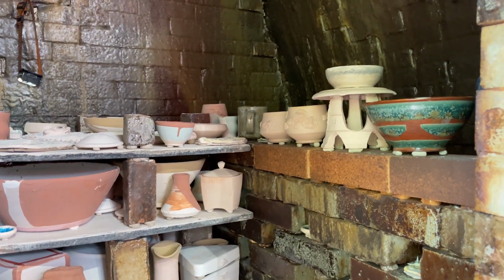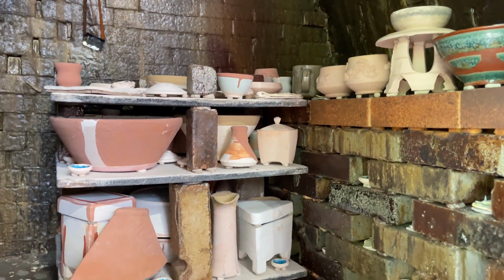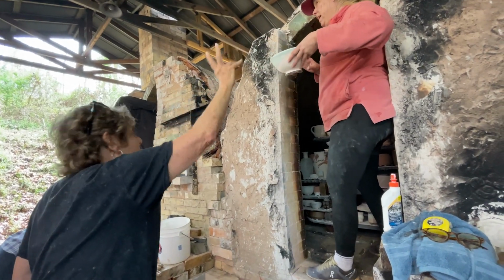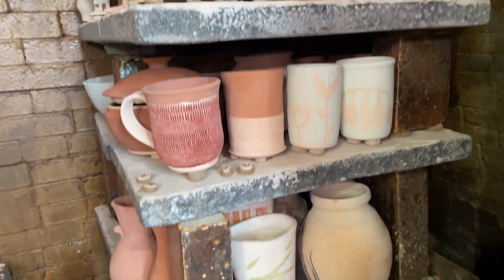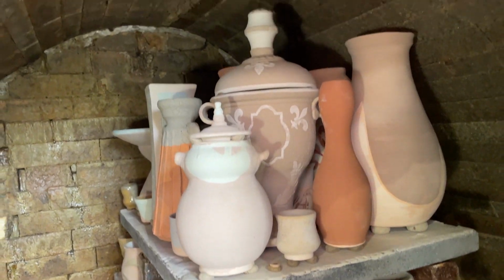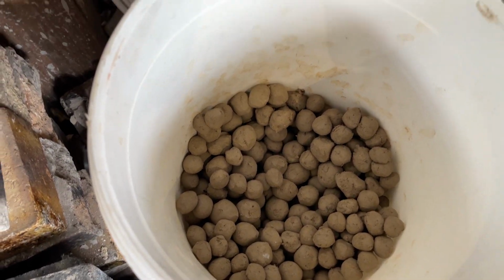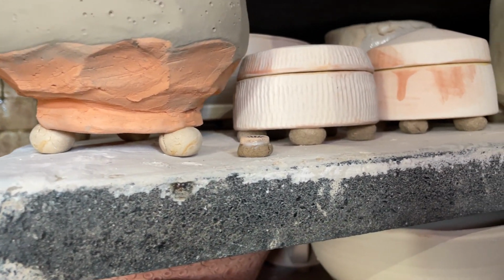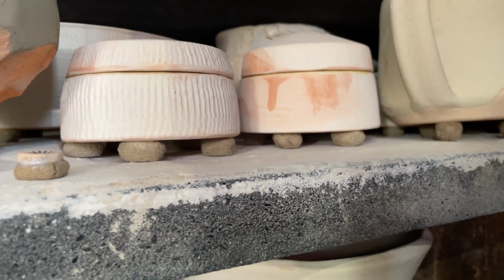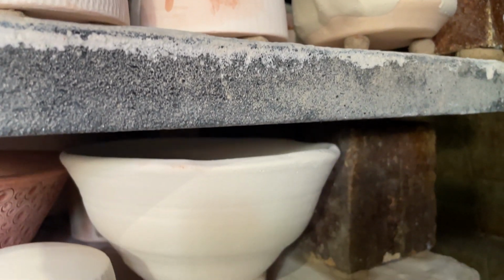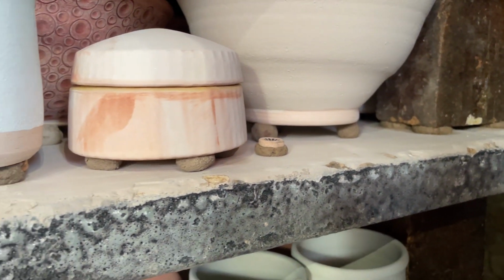You put the right pot in the right spot everywhere in the kiln, which is obviously impossible, but we do our best to do it. Certain glazes work better in the salt side and certain glazes work better in the wood side. In the kiln, there's volatile salts, potassium. Those things would all stick the pots to the kiln shelves. Everything would stick together. So we make a special clay wadding that then allows the pots to come separate from each other. Sometimes they're wadded touching each other on purpose to leave marks, and that way they come separated. So the wadding is basically protecting all the pots.